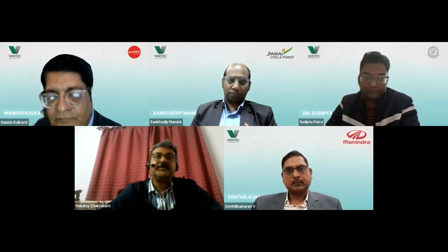Debale, there are a couple of questions. One is specifically addressed to you and one to you and Sudipta. Debale, how much can the transformation temperature be lowered when compared to niobium and vanadium? Okay, so in vanadium, nitrogen is very important. If we have nitrogen, it increases the equilibrium transformation temperature. And therefore, if we go for a relatively fast cooling also, very fine precipitates can form. And those precipitates are very stable. Compared to vanadium carbide, vanadium carbonitride precipitates are more stable. So you may find a lot of research using nitrovan for vanadium steels, because nitrogen increases the driving force for vanadium precipitation.